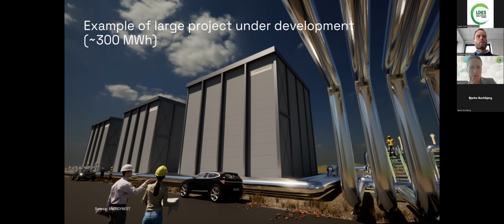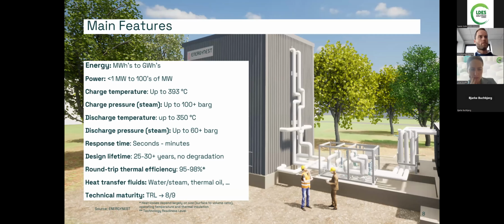So to summarize the main features of our technology. In terms of energy, we can do anything from a few megawatt hours up to gigawatt hours. On the power side, we can do anything from below 1 megawatt and up to hundreds of megawatts. And in the case of steam, we can charge with pressures up to 100 bar. We can discharge at temperatures up to 350 degrees Celsius. And in the case of steam, we can discharge at pressures up to around 60 bar.